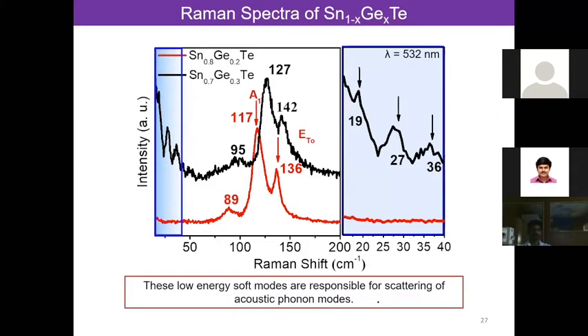In order to do that, we have done Raman spectroscopy, because Raman spectroscopy can track these low energy optical phonon modes. You see, this is the 20% sample. We don't see any low energy optical phonon modes. As soon as the 30% sample at room temperature, you see these low energy optical phonon modes, which are 19, 27, and 36 centimeter inverse. And this is coming from the ferroelectric instability in this material.